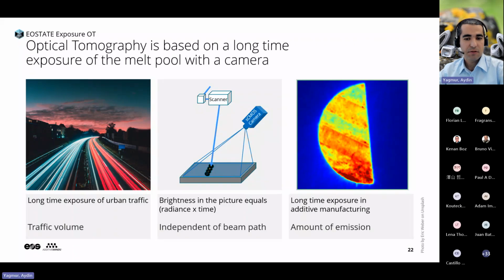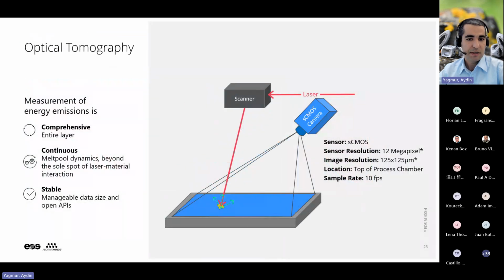OT records the data not only during melting, but also cooling down, also solidification until the layer is completed. So we have a different picture here. We see that a bigger area was influenced in terms of overheating, and this was detected by OT. And as I said, we can also see the spatter behavior. What lies behind this? Let's have a repetition. This is the camera taking pictures, 10 pictures per second during the layer time, and getting information, not only backscattered, but also any kind of emission created on the powder bed.